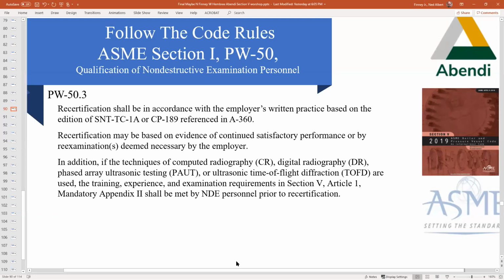PW 50.3, recertification shall be in accordance with the employer's written practice based on the edition of SNT-TC-1A or CP-189 as referenced in A360. Recertification may be based on evidence of continued satisfactory performance or by re-examination or examinations indicating one or more as deemed necessary by the employer. In addition, if the techniques of CR or DR or PAUT or TOFD are used, the training, experience, and examination requirements in Section 5, Article 1, Mandatory Appendix 2 shall be met by the NDE personnel prior to recertification.